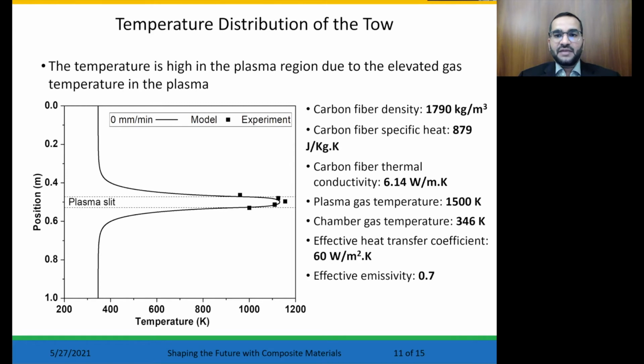The temperature profile of carbon fiber tow during the roll-to-roll deposition of graphene is shown here. The input parameters to the model include the properties of carbon fiber, which were taken from the manufacturer data sheet. The gas temperature in the vacuum was measured by a thermocouple. This value was used to represent the temperature in the pre-plasma region and post-plasma region. The gas temperature in the plasma region was estimated from the emission of hydrogen, which was measured using optical emission spectroscopy. The effective heat transfer coefficient and effective emissivity from the tow were used as fittings to the model, as shown in this figure.